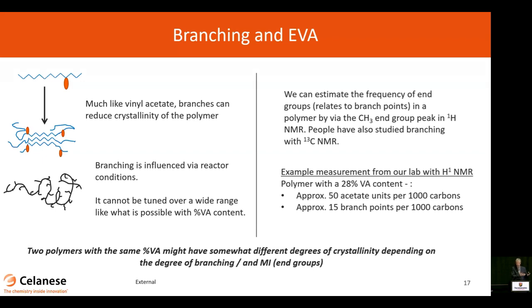So you see that there's a lot more acetate units than there are branch points, but there's still a significant amount of branch points, and those are going to impact crystallinity. The difference is we can tune the acetate units from 0 to 100 per 1,000 carbons, and we can only move the branch points a small amount. So we can't use that as a practical tool for changing the release characteristics that you get from a system, but it will have an effect. And a practical consequence of this is potentially two different materials with the same vinyl acetate content could have somewhat different crystallinities.